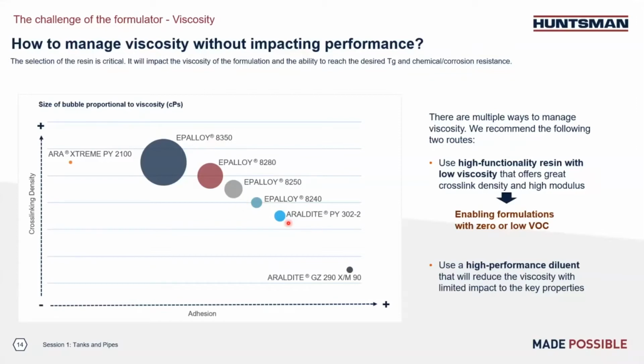We also have another resin such as ARALDITE PY 302-2. So this is kind of a bis-A/F mixture type resin. And so it has lower viscosity than typical bis-A type resin, but it also has a better chemical resistance than typical bis-A type resin. So sometimes we use this kind of resin for floor coating applications.